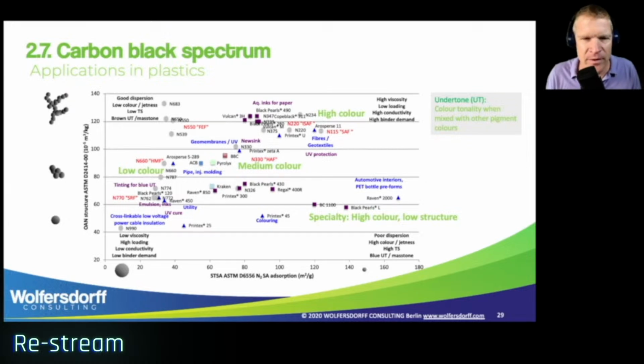And we have the semi-reinforcing, also called low color, on the left-hand bottom. In the middle of the chart, we have medium color. This is the rubber black N330, for example, which is also called high abrasion furnace, HAF, carbon black. Then we have higher surface, providing higher color. And the higher surface is a smaller particle. So here already we can say smaller particle has a higher color.